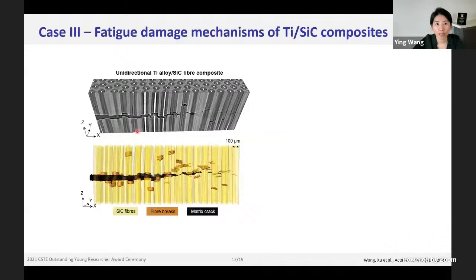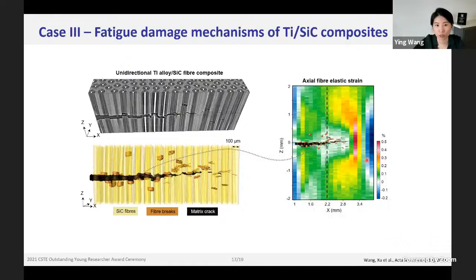And here shows, with the fatigue crack, the damage morphology near the fatigue crack tip, where we can clearly see the crack path distribution. The black here is the matrix crack path, and the brown discs here are where the fiber breaks are. We can also correlate this information with the strain distribution around the crack tip. From this strain distribution, we can also calculate the interfacial sliding stress under fatigue and see how the fatigue and the heating damage the interface and degrade the interfacial properties. This is really helpful for material scientists to design the interface and balance the properties between the fibers and matrix in this material system for longer fatigue life.